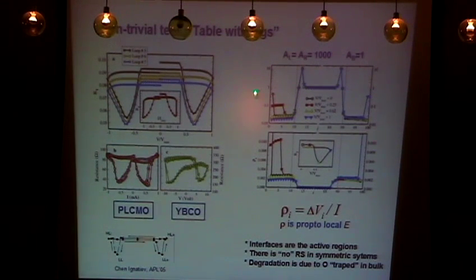Now you go into the positive part, and in the positive part you start pushing these vacancies out from the extreme left region. The reason is that since we have most vacancies there, the resistance is going to be much larger there. Remember that the resistance is connected to the vacancies through this parameter A, which is much larger here and here than in the middle. So these vacancies have a big effect, so you have a large resistance up there, and the resistance is nothing but the local electric field, because since this is a one-dimensional system, it's serial, so the current is the same for all the layers, so the voltage drop is directly proportional to the resistivity. Therefore, the resistivity is a measure of the local electric field. So the local electric field there is large. Therefore, that's why you push the charges from this extreme into the system.